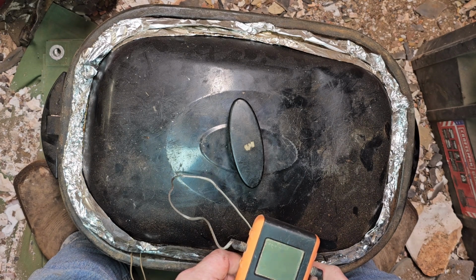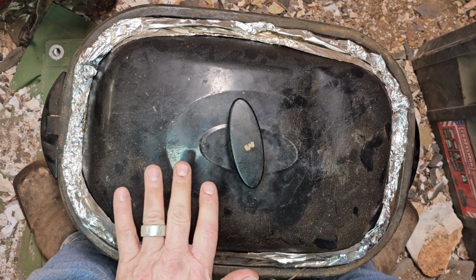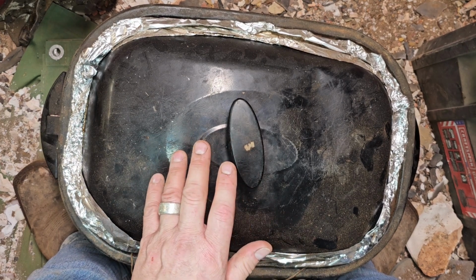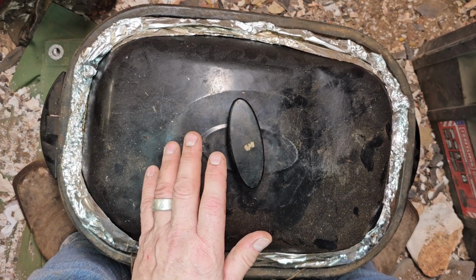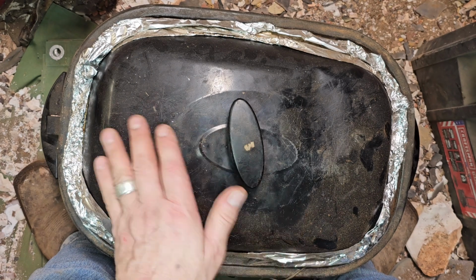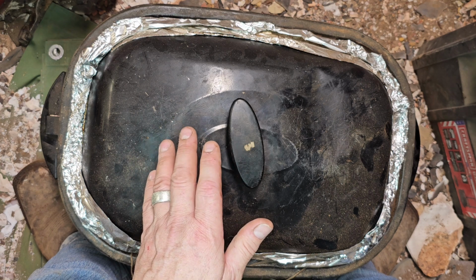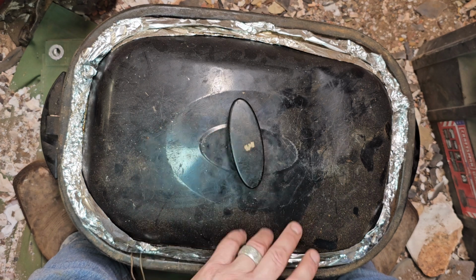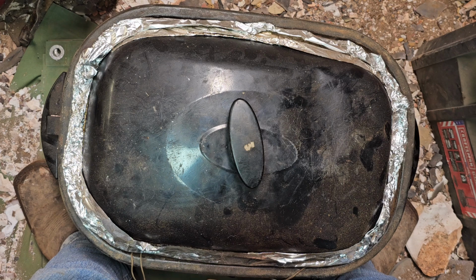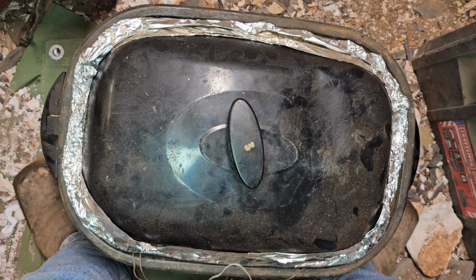And it's cooled down. I don't pop the lid on this till it cools completely down. If you pop this lid to take a peek and it's cold outside or wherever it is you've got this, that cold air rushes in. It doesn't have to be real cold air. The colder it is, the worse it is, but just cool air can rush in, and you can hear it just go tee, tee, tee, and you just hear microfractures shoot throughout the material.